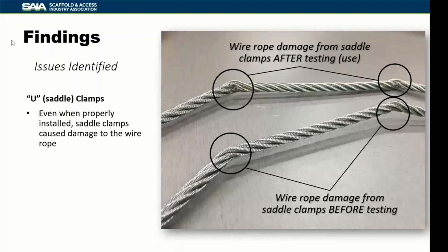And if we look at the wire rope both before and after, if we just take the clamps off before we've put any load on it, you can see the deformation that has occurred in the wire rope. And then after the test, you can see how that deformation has been exaggerated. So if you were to ever use U-clamps, it is absolutely apparent that you would never be able to reuse that wire rope again because of the damage that has been done